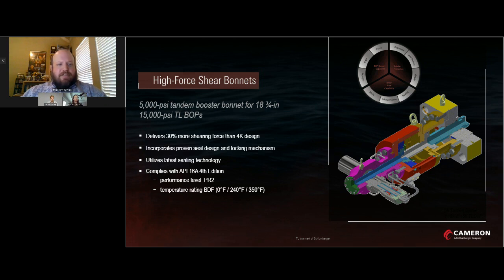What you see here is the layout of our new 5,000 PSI rated working pressure tandem booster bonnet that would be applied for shearing and sealing applications on an 18 3/4 15K BOP stack. This bonnet increases the rated working pressure from 4,000 PSI that current rigs use today up to 5,000 PSI, which results in about 30% more shearing force because we did some geometry changes as well. So the pistons are slightly larger and the pressure is higher. So we can get that extra shearing force to get some of these heavy strength tubulars.